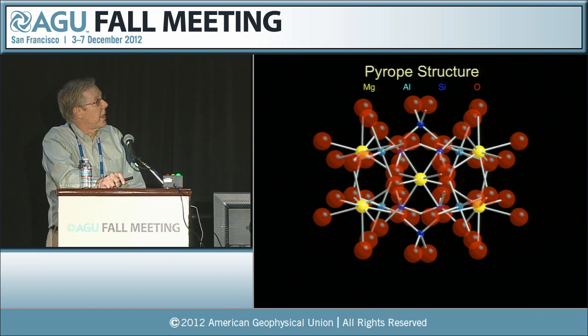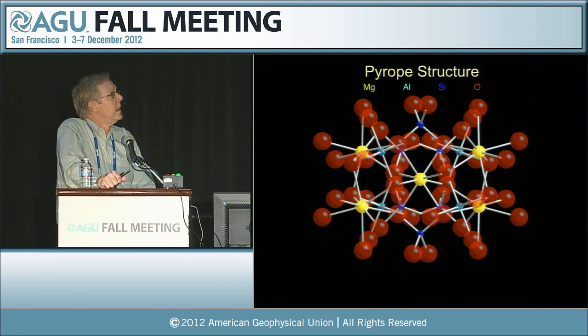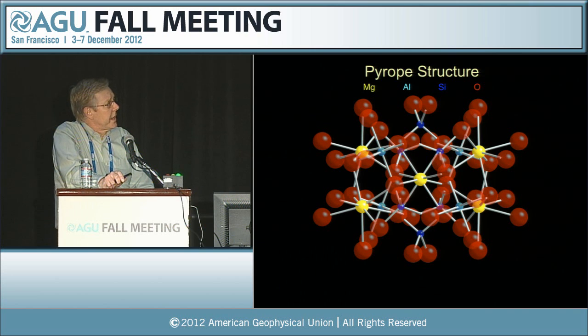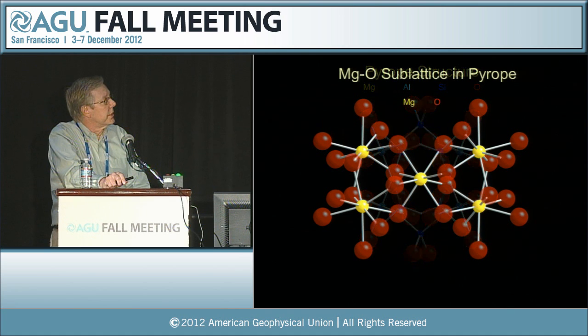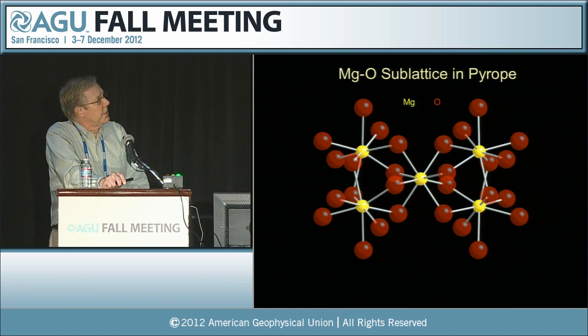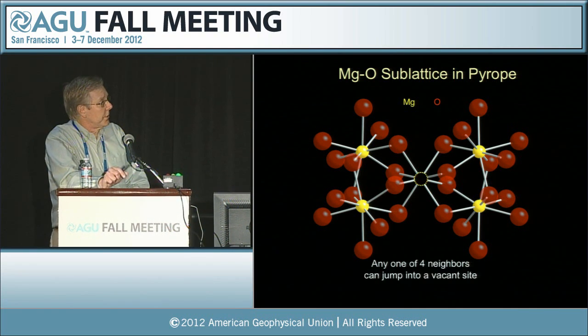Here's a little piece of the pyrope structure. You can see tetrahedrally coordinated silicon in dark blue, octahedrally coordinated aluminum in light blue, and the atoms of primary interest are the yellow ones, which are in eightfold dodecahedral coordination. And if we focus in on those, you can see that each of those dodecahedra shares 4 of its edges with neighboring dodecahedra. So if we introduce a vacancy in the center, any one of those 4 neighbors could jump into that vacant site in diffusion.